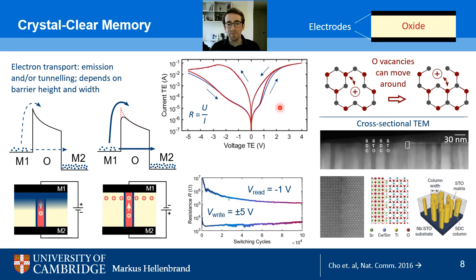Now, on the contrary, while no charge is involved here, we store the information in the resistance state of this structure here. So the position of oxygen vacancies either close to the interface or away from the interface. This is very different from storing charge, because the charge in current technologies is stored in the form of electrons, which can move around very easily, whereas oxygen vacancies, if you remember, require more energy to break the atomic bonds and to move them throughout the oxide.